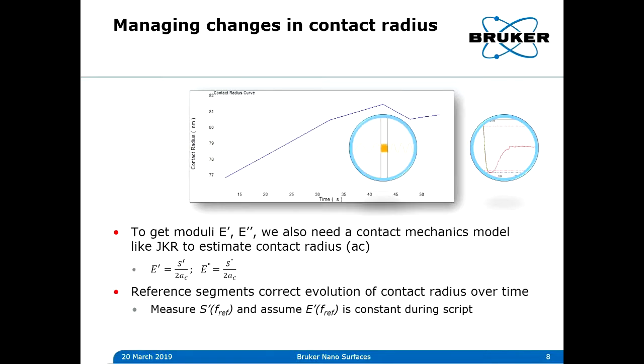So what we do is we add reference segments all with the same frequency throughout the measurement, and one right before the retract. We measure the contact radius during the retract using the JKR model, and then we can use these reference segments to correct the contact radius at earlier times by interpolating between them. So here is a plot of contact radius versus time in one of the measurements.